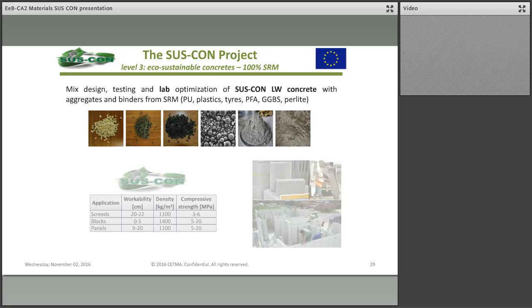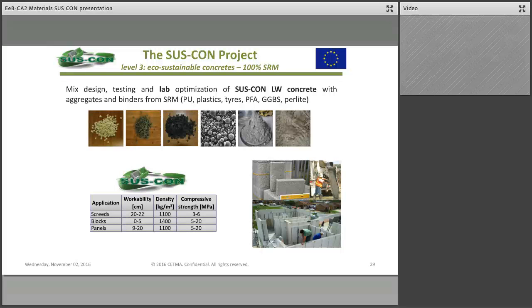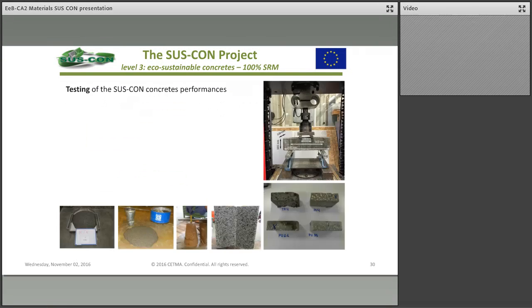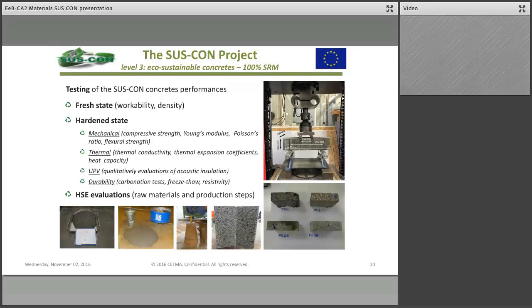So Suscon lightweight concrete with aggregates and binder from secondary raw material were designed and tested, targeting specific products like screed, blocks, and panel. All the concretes were developed and optimized in the industrial plant, aiming at optimizing the fresh state and hardened state performances, just like workability, density, mechanical, thermal, and also durability performances, and HSE evaluation of both raw material and production steps was also performed.